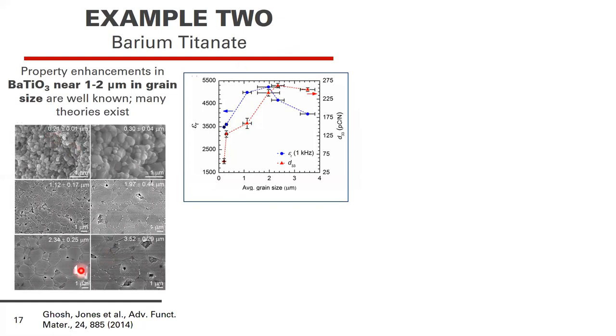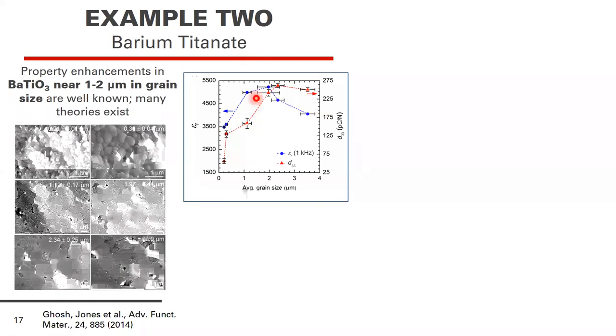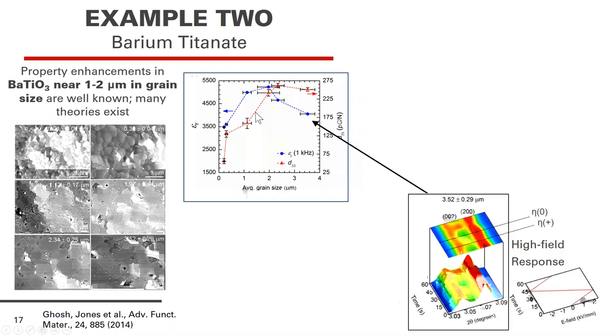And we deployed these types of analytical approaches to describing the degree of domain switching in this set of samples. Now, one thing to really remember about barium titanate is that around a grain size of 1 or 2 microns, there's a peak in properties. And throughout decades of literature, there are various theories about why there's an increase to properties. And we thought these tools would be useful for characterizing this.